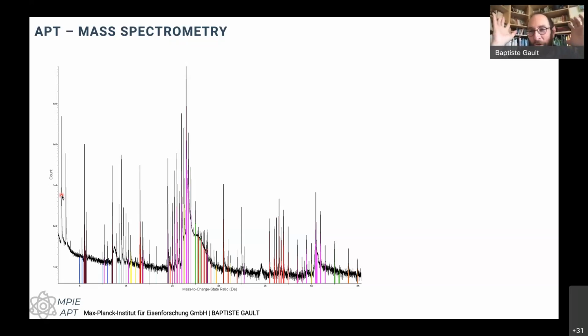So we are not completely done with this. So what we are doing here increasingly, so there's 2 aspects. So first we try to introduce deuterium instead of hydrogen, and then in principle, if we are in the right analysis conditions, we should have mostly hydrogen coming at 1 and not at 2. So everything that is going to be in the peak at 2 Dalton should be deuterium, which we have introduced, especially introduced inside of the microstructure. And there we can actually look at where it's sitting inside of the microstructure.